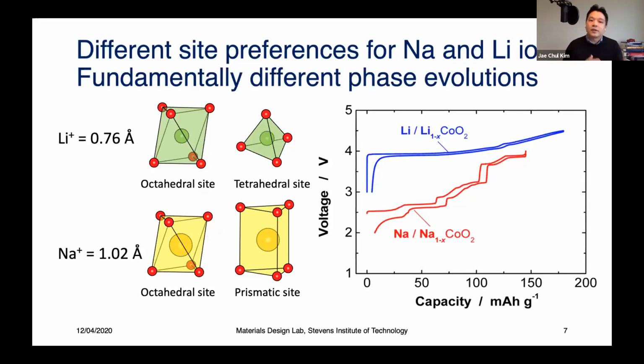As you know, lithium is pretty small. Lithium ion is about 0.7 angstrom, whereas sodium is much bigger. It has about 30% larger ionic radius than lithium, so it's about 1 angstrom. This leads to a different site preference in the material.